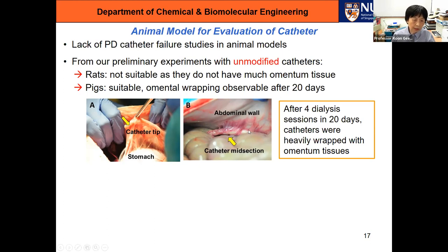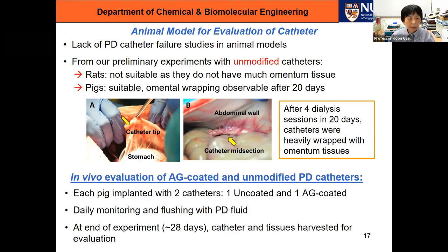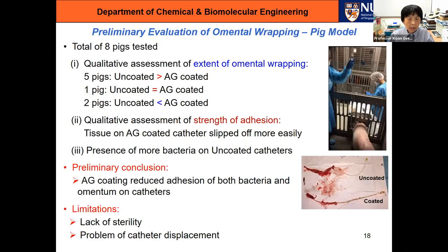When we carry out our experiment, we take one pig and implant it with 2 catheters, an uncoated catheter and an agarose coated catheter. Every day we flush the catheters with PD fluid, which is what patients would do. And then we monitor the pigs. At the end of the experiment, which is 28 days, we take a look at the catheter. We managed to test 8 pigs. This is what it looks like. This is the dialysis fluid here, and it is just put into the pig by gravitational flow. And the catheter is inserted into the pig.